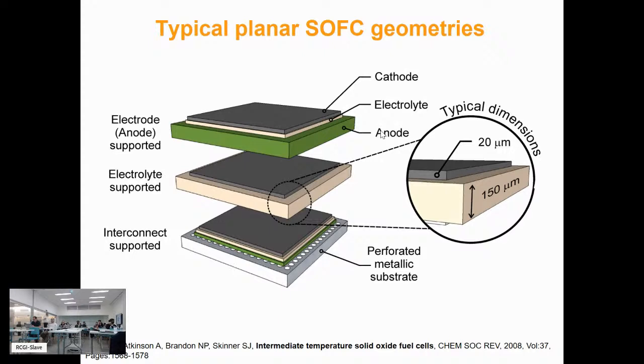The mechanical support is made of a porous composite material. The other is to use the electrolyte as the support, which then needs to be thicker. This is about a 20 micron thick electrolyte. This is about 150 microns thick. The material with the lowest conductivity and the highest resistance is the electrolyte. So the thicker the electrolyte, the higher the resistance, the lower the power density, and the less the efficiency.